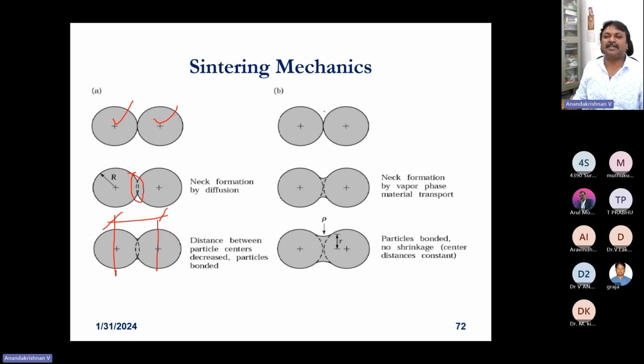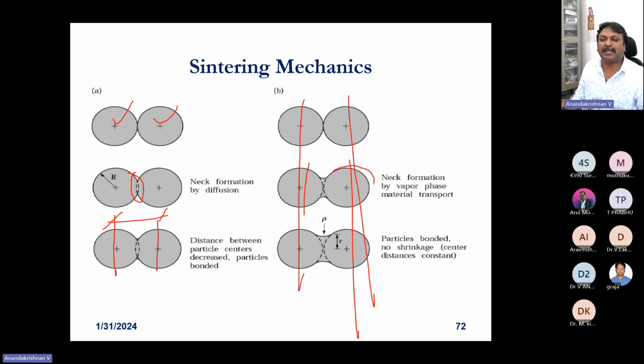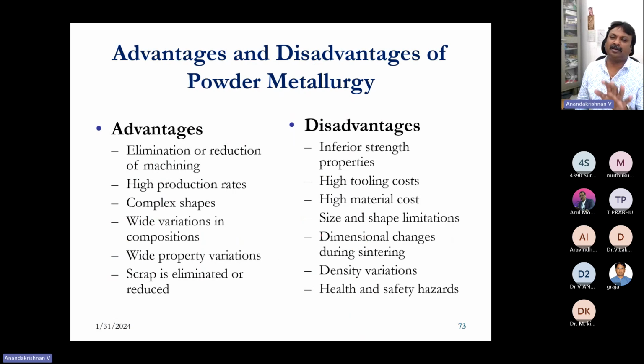Whereas this is another way of doing it. See here, the center distances are not at all disturbed, and only the outer layers of the particle get melted due to surface tension, forming a meniscus, and then they get fused. For this, people are working on metal particles coated with a lower melting temperature material so that they fuse together, and it's also under research. Coated powder particles can be used for additive manufacturing. Up to my knowledge, nobody has done it.